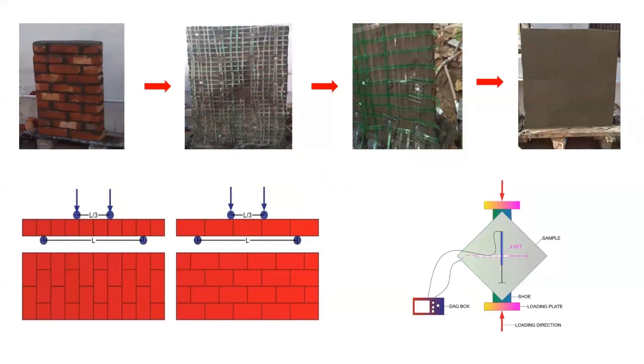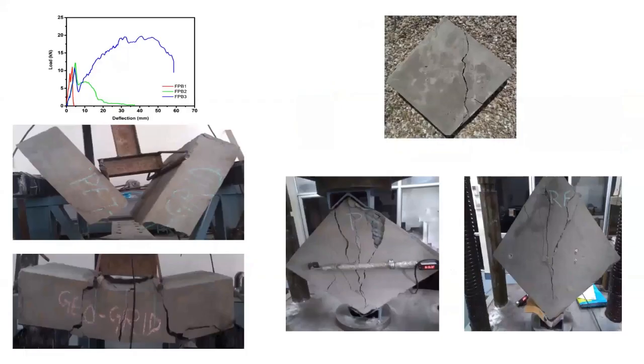And we strengthened the wall like this. And after this, we studied bending, parallel and the joint, and then diagonal shear behavior. So obviously, in tension behavior also, it shows that after reaching the peak, it had a drop. So it's a brittle material. So we experienced a brittle failure. So this is the PET water bottle based textile. But the beauty is the conventional sample failed in a brittle way. And the PET water bottle shows you that green color is a PET water bottle. I will change the color.